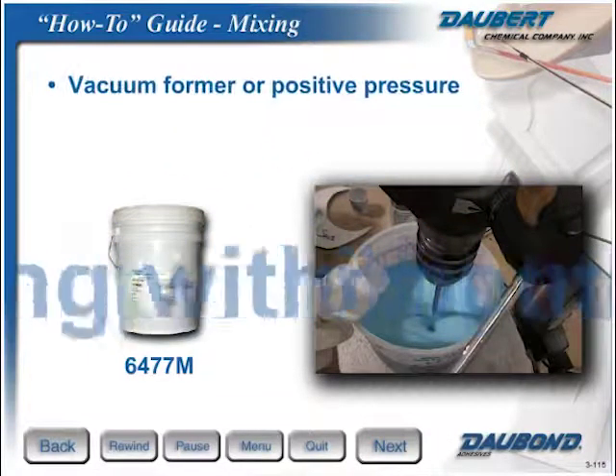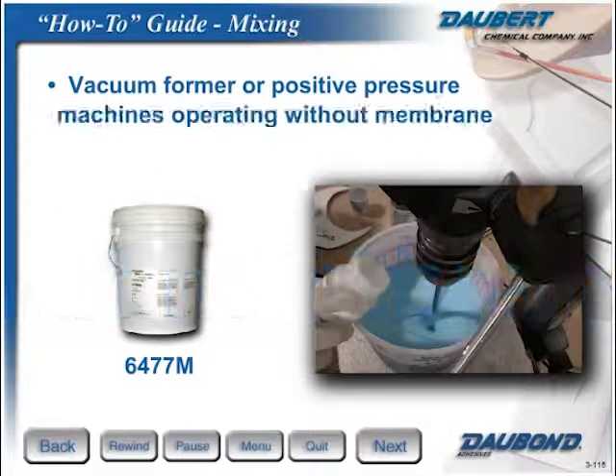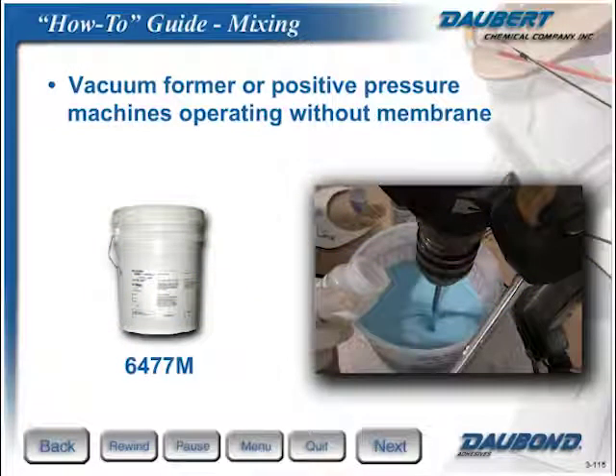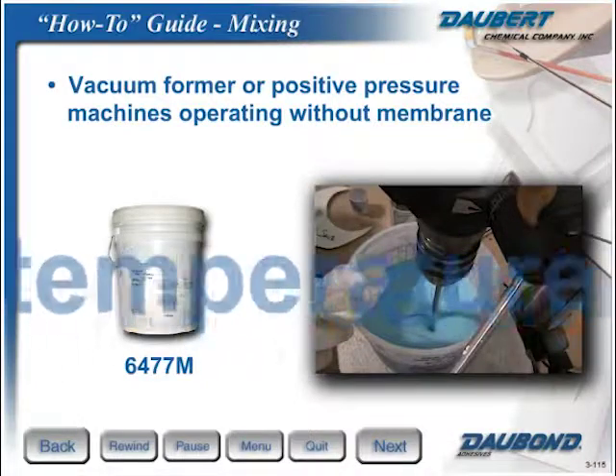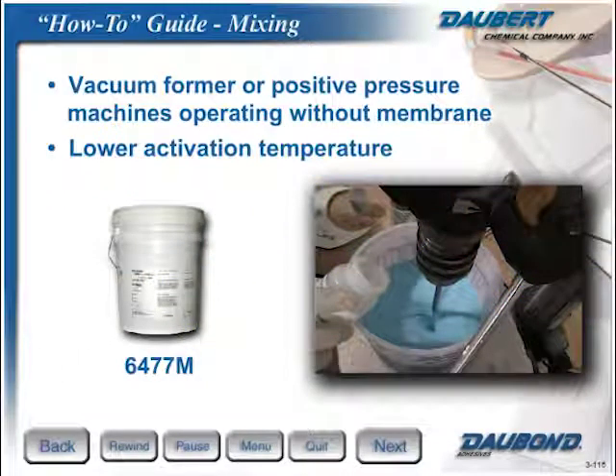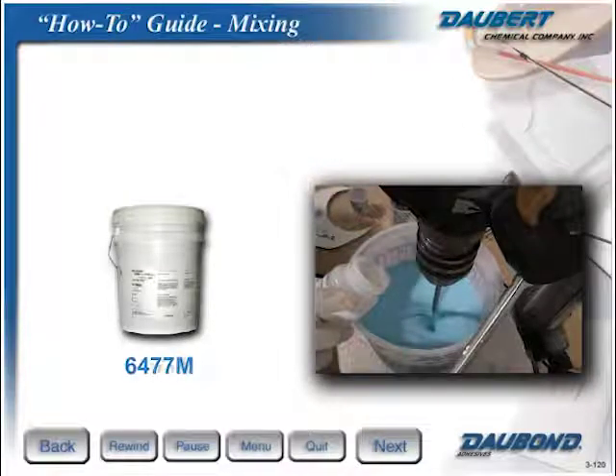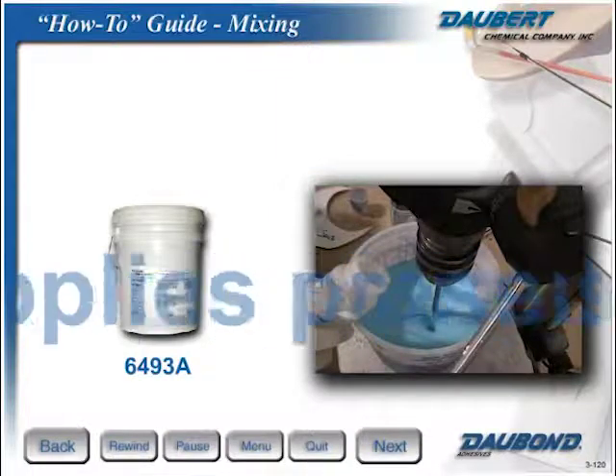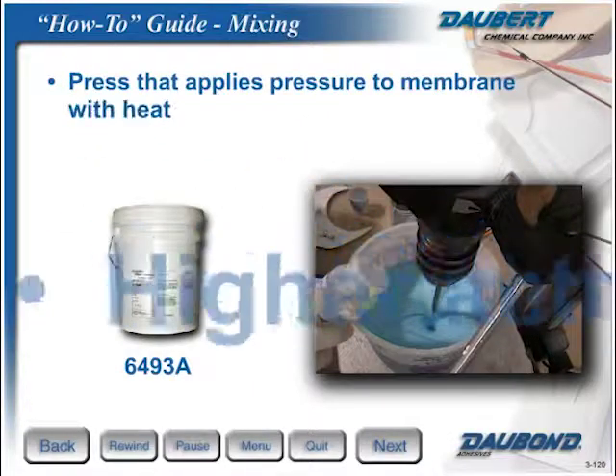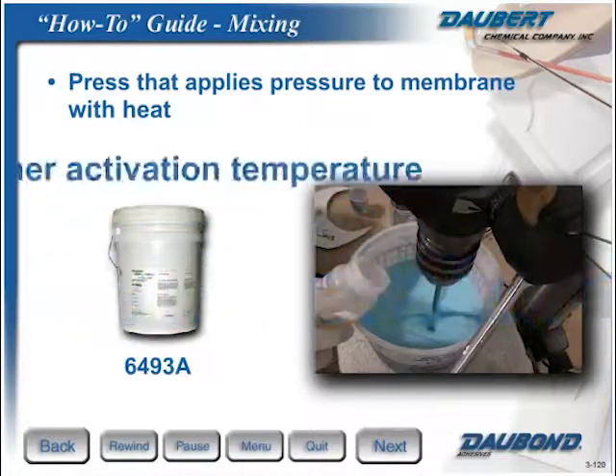If you have a vacuum former or positive pressure machine that operates without the membrane, we recommend 6477M. This adhesive has a lower activation temperature, which gives you a wider operating window for this type of press technology. If you're using a membrane press, then we recommend using 6493A. In a membrane press, the vinyl and the membrane come down, delivering more heat, so you can use a higher activation adhesive.